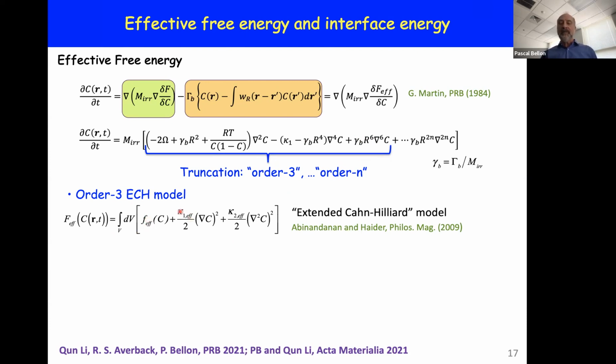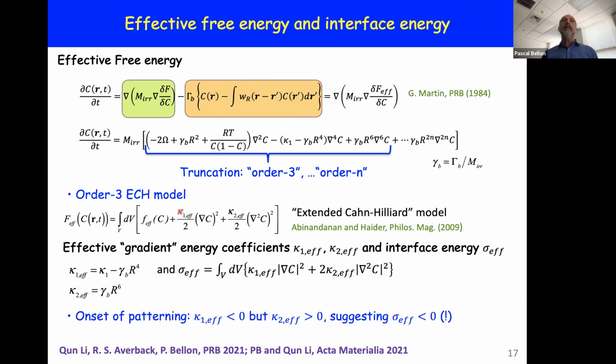There's an effective gradient energy coefficient, kappa 1 effective, and there's a new term that's proportional to the Laplacian of C to the second power. So often this is referred to as an extended Cahn-Hilliard model. And for a model like this, we can calculate an effective interface energy as well.